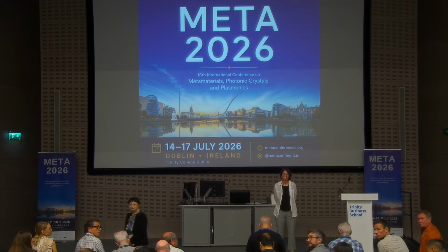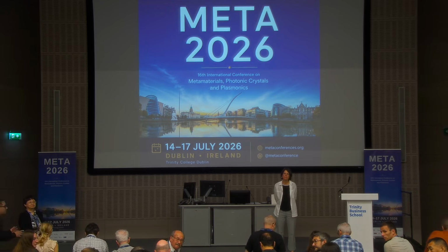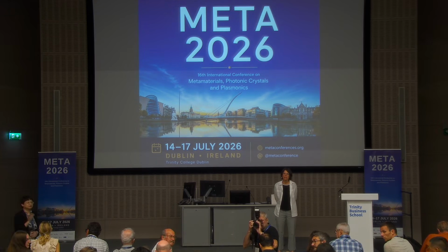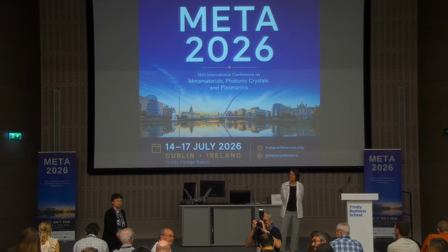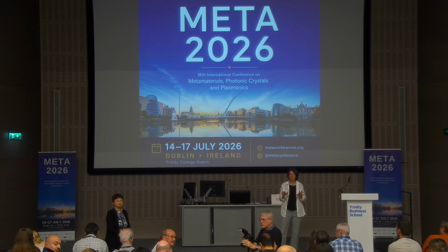Okay, thank you. Rachel, thanks for the nice talk. I have a question. In this sol gel process, I see you have more knobs than just crystal growth. So can you affect coherence length significantly, for example? Or have you tried measuring that in your sol gel films? I don't think you can affect coherence length because it will depend on the material itself. You can affect electro-optic properties. You can pole the sol gel, actually. Right, but because you have porosity and also the chemistry, maybe you can affect the indices, and then your coherence length can change. So is that significant?